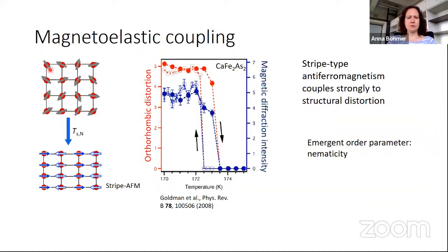So if we go from this state to this one, we go from something that's a square here, the material itself, it's called tetragonal, but the iron lattice is just square, to something that is no longer square, because this direction is just different from this one. So just by symmetry, this cannot be a perfect square at least. If we measure this, we find it's not a perfect square.